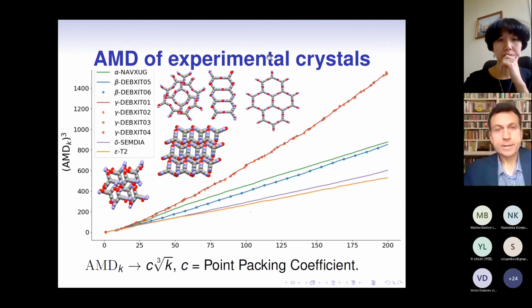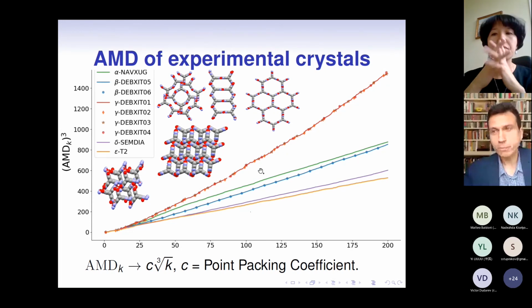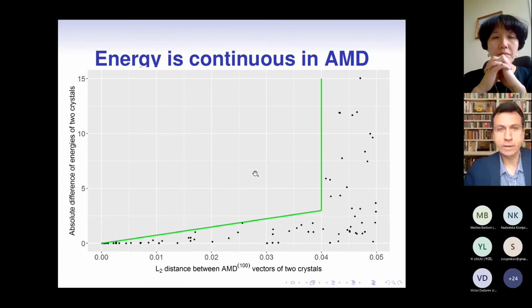Right. So this slide shows experimental computations for 9 experimental crystals, and let me go quickly to the continuity statement. So you see when the difference between AMD vectors changes slightly, the energy changes slightly, and this picture is very different from the previous one when we considered RMSD and powder X-ray diffraction patterns.